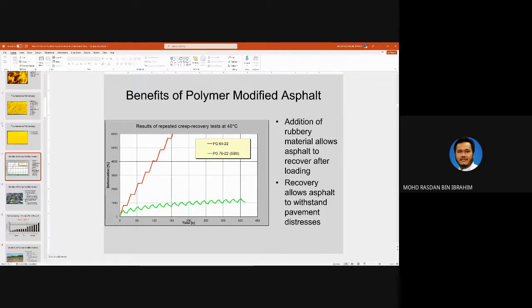So the recovery is able to span higher number of load repetition. So you can see from this graph, the PG64 not modified with SBS here, the deformation occurs in this creep test, actually occurs very early, 150 seconds, and the PG 76-22 modified by SBS here, it took a very long time for the deformation to increase.